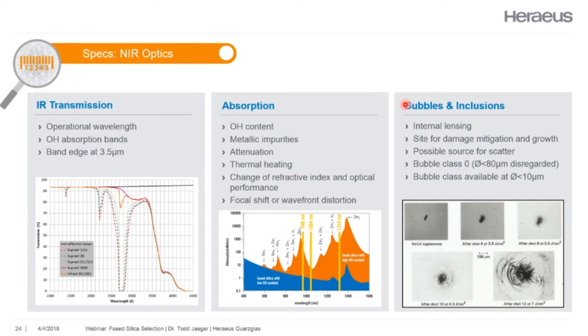Additionally, if you have bubbles and inclusions, the high power laser can go through internal lensing. The bubbles and inclusions themselves are sites for damage initiation. And unfortunately, as you can see from the picture here, once the damage starts, it doesn't get better. It gets significantly worse with each laser shot. Now at Heraeus, we spec a bubble class 0 as a material that doesn't have any bubbles larger than 80 microns in it. We also have a special bubble class that's available with no bubbles in it larger than 10 microns, which is available on special request.